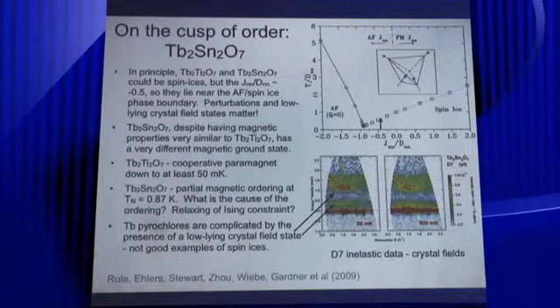And very subtle crystal field effects at low temperatures can influence the ground state. Terbium titanate is a cooperative paramagnet down to 50 millikelvin. Terbium stannate has this partially ordered state. People are still trying to understand. It could be due to relaxing of the Ising constraint. There's some discussion of that this week.